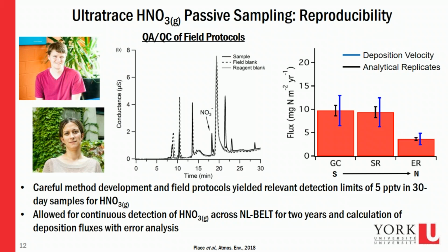And the QA/QC protocols that we put into place, which is literally taking stock of every single thing that you touch that you could possibly manage to transfer nitrate from some other surface onto your sampling substrate. We pay very close attention to that, and we effectively have no difference in the nitrate levels in our field blanks compared to our solvents. So we get nice quantitative measurements out of these particular samplers.